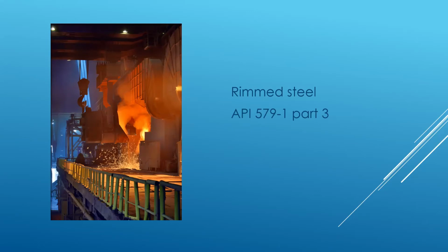So I had a client that wanted to know if his pressure vessel, which was just about 50 years old, was made out of rim steel. Rim steel, so if it comes out of the open hearth furnace, it's at the carbon and silicon content we want and the manganese content, but it's saturated with oxygen. Now we have to get rid of the oxygen somehow. Oxygen gives us really bad impact toughness, right? So one way to get rid of the oxygen is we allow the steel to rim.